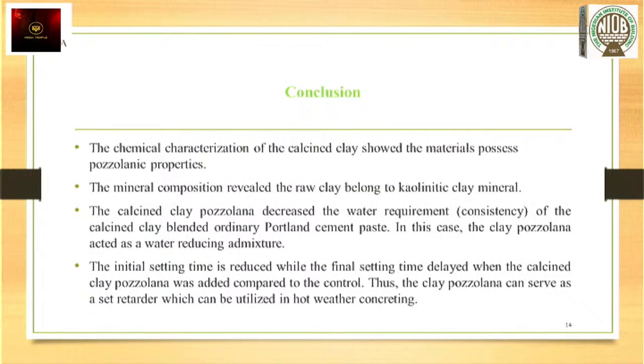So in conclusion, the chemical characterization of the calcined clay showed the materials possess pozzolanic properties. The mineral composition revealed the raw clay belonged to kaolinitic clay mineral. The calcined clay pozzolana decreased the water requirement, which is the consistency of the calcined clay blended ordinary Portland cement paste. In this case, the clay pozzolana acted as a water-reducing admixture. The initial setting time is reduced, while the final setting time was delayed when the calcined clay pozzolana was added to the OPC. Therefore, the clay pozzolana can serve as a set retarder, which can be utilized in hot weather concreting. Thank you for listening.